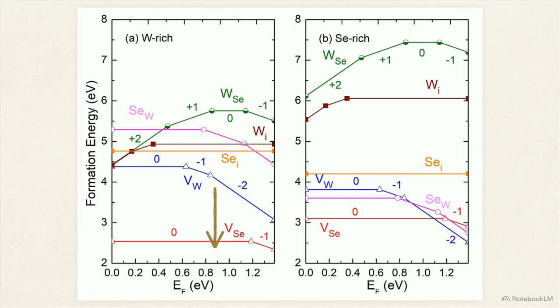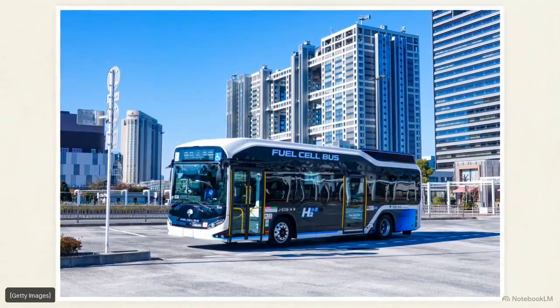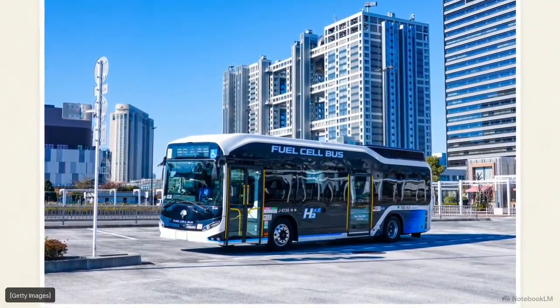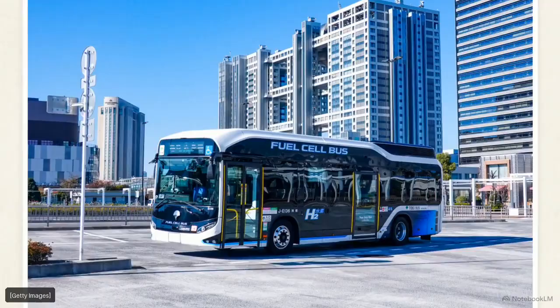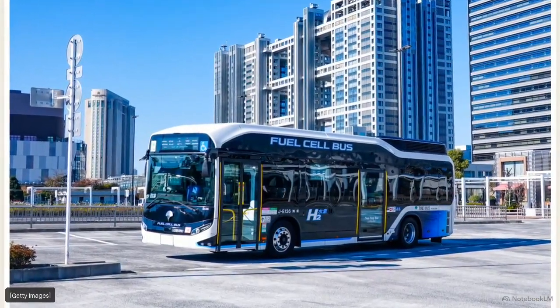At the neutral charge state, removing selenium leaves unsaturated tungsten coordination sites that act as powerful, highly active catalytic hotspots. These missing atom gaps violently attract passing oxygen and water molecules. The kinetic interaction at the hotspot rips the chemical bonds apart, forming the oxide intermediates that facilitate the reduction and evolution reactions required to generate hydrogen fuel or store energy in a battery.